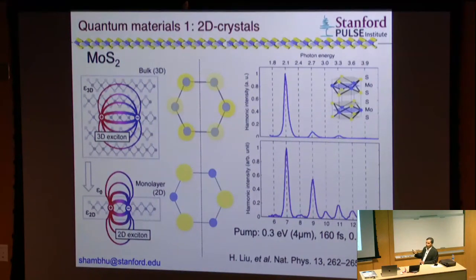The working explanation is that, as we shared before, there are two mechanisms. One is the intra-band, single band mechanism. Another is the two-band mechanism. And it turns out that for high order harmonics, which are above the band gap, one mechanism dominates over the other. And the other side of the band is the reverse. So that comes into play, and to explain this, you have to use this fully quantum mechanical model, because these dynamics get coupled, right? So there is no easy explanation, but there is a fully quantum mechanical model that considers it's not the simple inter and intra band picture, right? Things are coupled, so that does reproduce this increase, and I suggest you find our recent paper. That's what we talk about. The paper is in Ultrafast Science. That's the new journal.